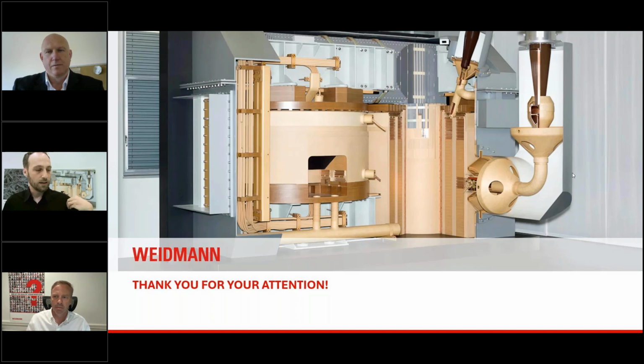And as a small add-on to the question, when we are already discussing these scales, right? If you look at the amount of oil in a transformer and the amount of cellulose in a transformer, and you remember that for oil you use ppm and for cellulose you use percentage points, then it becomes quite quickly evident that actually the large amount of water that remains in the transformer in service really comes from that remaining part in the cellulose, and that the oil is only 1 to 2, 3%, right? So this is why it's so crucial to dry the cellulose, because you can only dry it so far, and that you really have to do. And even if you do it correctly, the major amount of water in the transformer will come from the cellulose insulation.